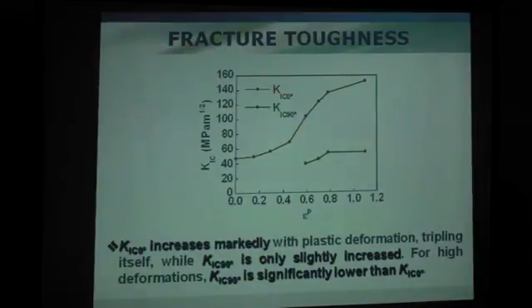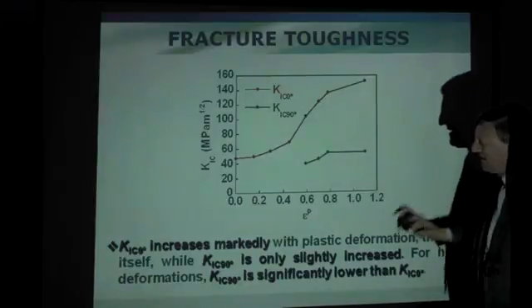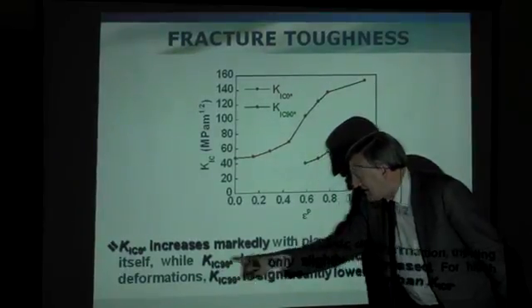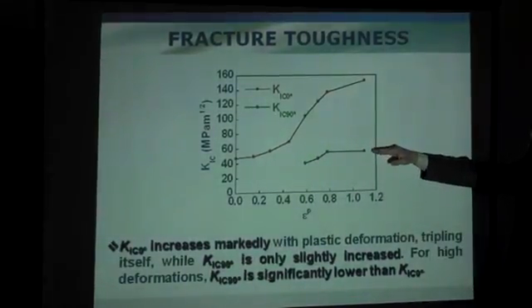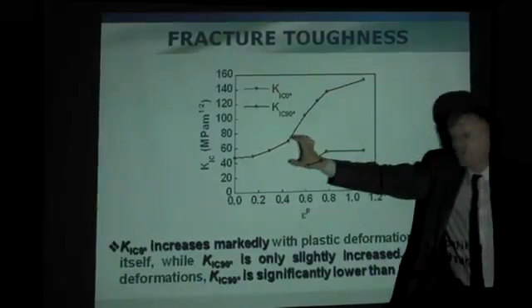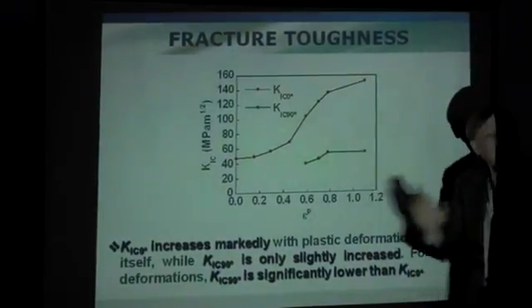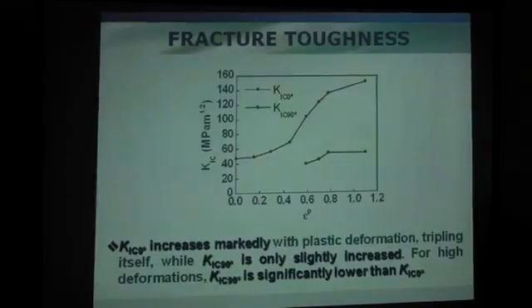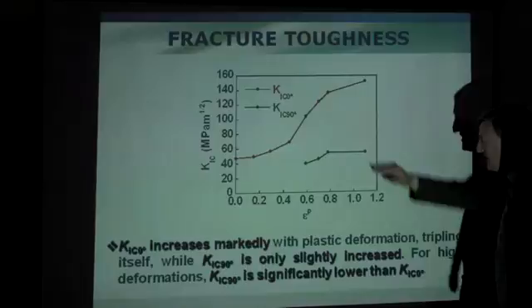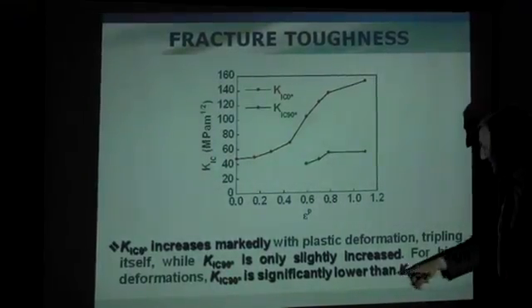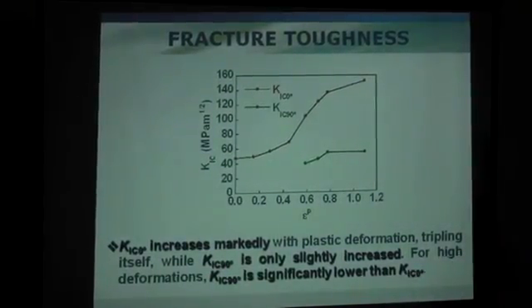But the problem is this splitting, this crack branching, this debonding of the lamination, because while K1C 90 degrees is only slightly increased, it's almost constant, roughly speaking. There is no improvement with regard to the debonding or the lamination. That's sad, but that's what happens. For high deformation, K1C 90 degree is significantly lower. This is the weakest phenomenon than K1C 0. That's the problem with prestressing steel. This is an anisotropic fracture.